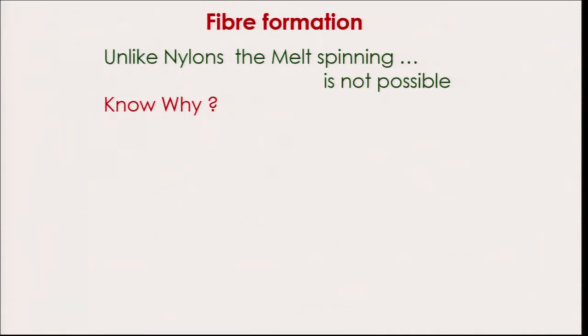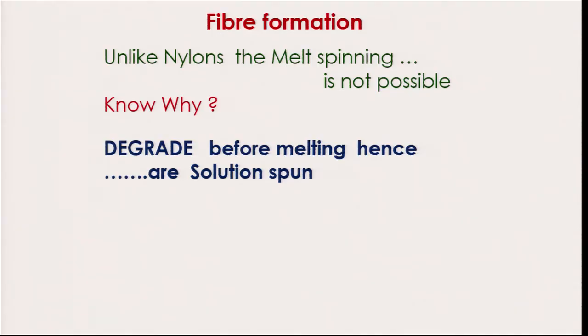Now, unlike the normal nylons, the normal synthetic polyamides, nylon 6 and nylon 6,6, we cannot melt spin aramid. You know why? Can anybody answer why? The reason is it degrades before it melts. The melting point is higher than the degradation point. Like cellulose and acrylic, they degrade before they melt, right? So, you cannot spin acrylic by melt spinning commercially. So, these are also solution spun, like we spin acrylic fiber.